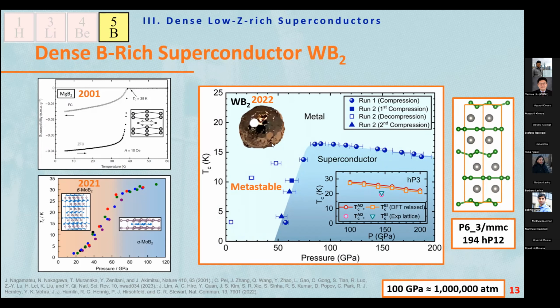I took just a small piece of the sample from the surface and squeezed it in the diamond anvil cell. And indeed, we found that superconductivity appears above 50 GPa. And it's not decreasing, but increases with pressure. It keeps going up to 70 Kelvin, which is a relatively high TC in superconductivity, and gradually decreases afterward. And an interesting part is that when we did the pressure release measurement, superconductivity appears at lower pressure, showing that this superconductivity is metastable.